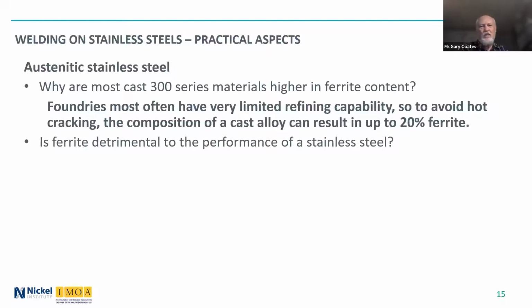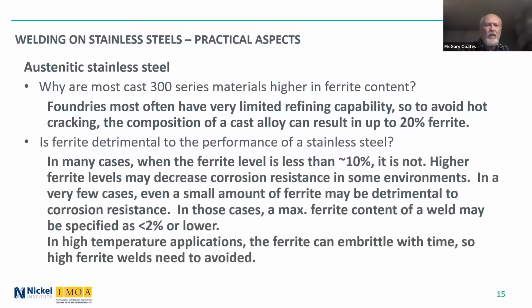And you might ask, is ferrite detrimental to the performance of a stainless steel, corrosion resistance, or high temperature properties? And the answer is, yeah, in many cases, it can be. So when the ferrite level is less than 10%, it is generally not detrimental. But higher ferrite levels may decrease the corrosion resistance, not in every environment, but in some environments. And even a small amount of ferrite may be detrimental to corrosion resistance in a very few cases. And often in those cases, the engineering company involved with the welding will specify a maximum ferrite content in the weld of 2% or even lower. For urea grade materials, they often say 0.6% maximum ferrite in the welds.